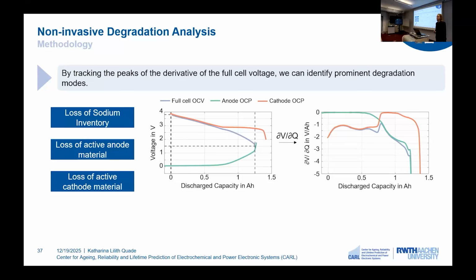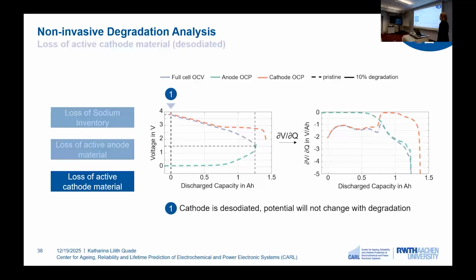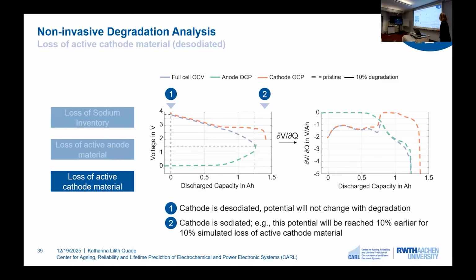And I now want to illustrate this with a simulated 10% loss of active cathode material in the desodiated state. So let's have a look at that. So we have a loss of active cathode material in the desodiated state. This means we're starting here at the 1. And when the cathode is desodiated, this means that our full cell is charged. And this potential that you can see here will not change with degradation. However, here we can see the second point. Here the cathode is sodiated, and now this potential and all other potentials will be reached 10% earlier for a 10% simulated loss of active cathode material. And mathematically speaking, this corresponds to a compression by 10%.